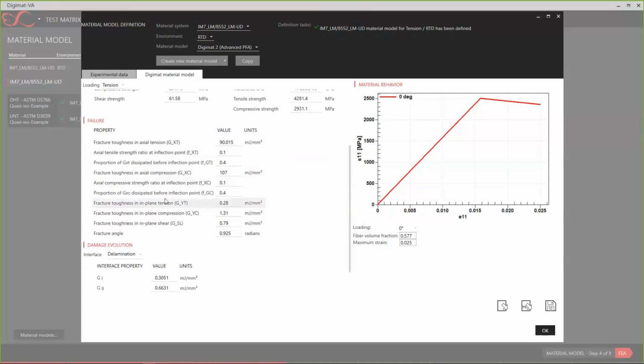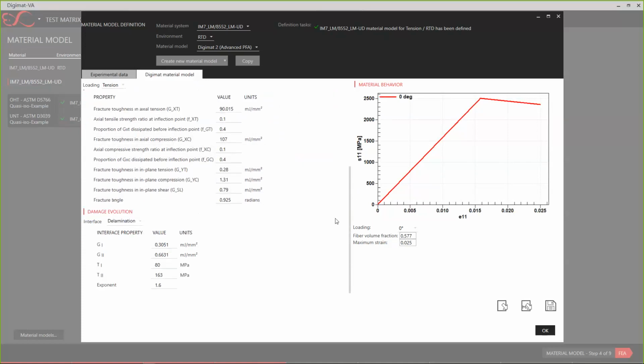Then the last thing that we need to define is the interface property for the delamination. Like I explained, we need the fracture toughness in mode 1, in mode 2, and the delamination stress, or the damage initiation stress, in mode 1 and in mode 2.